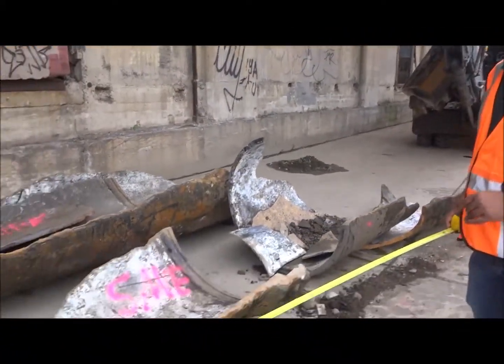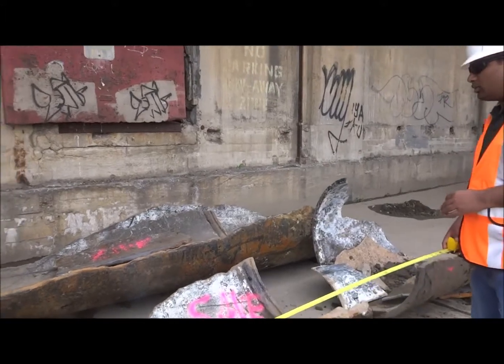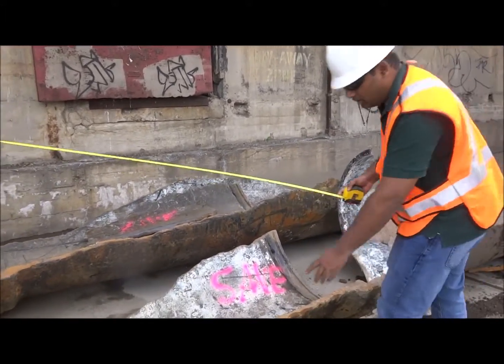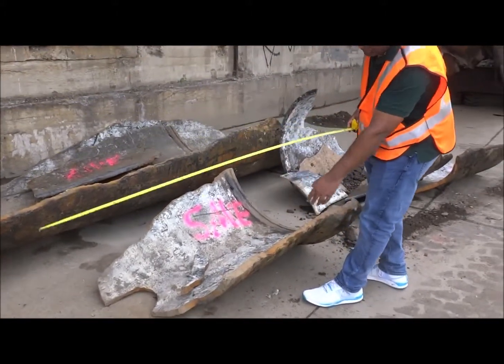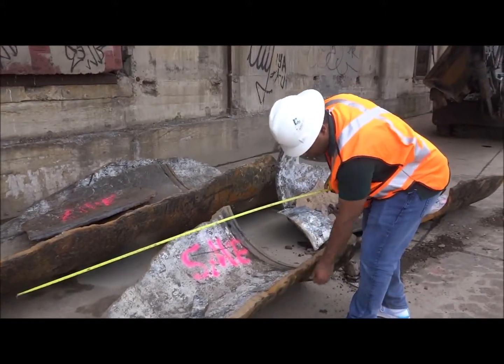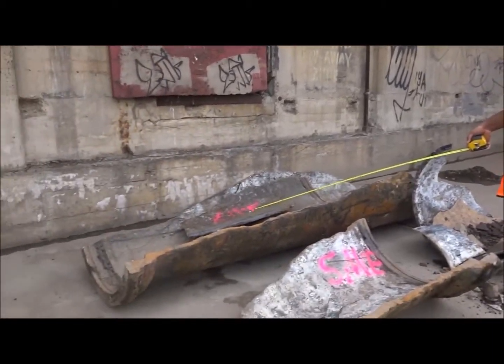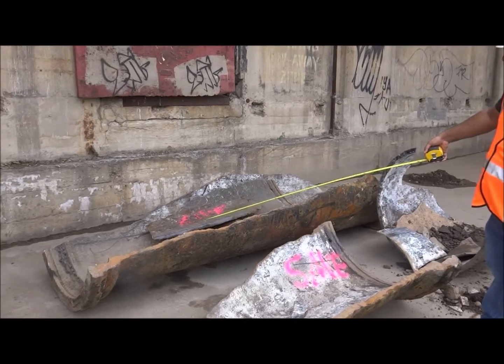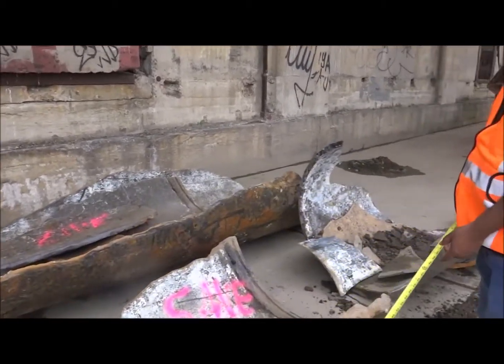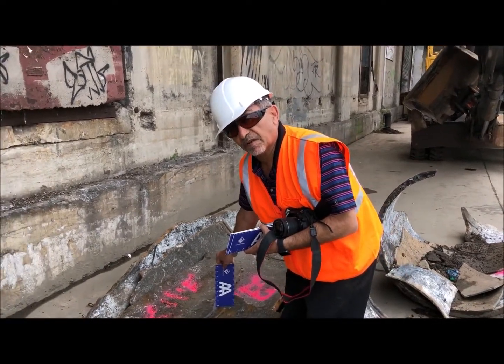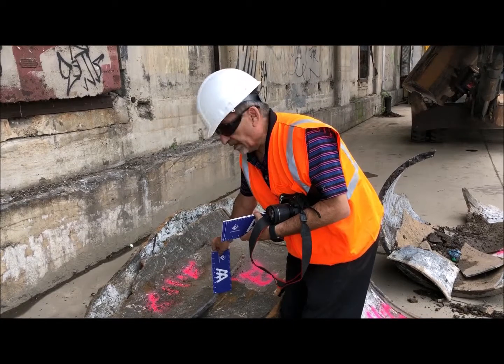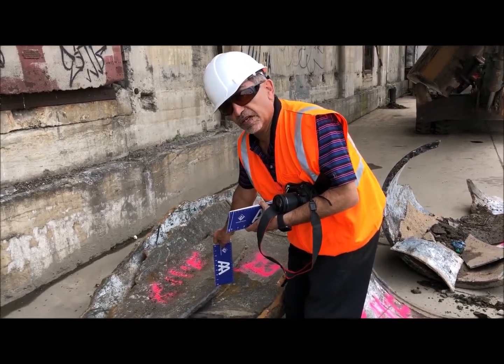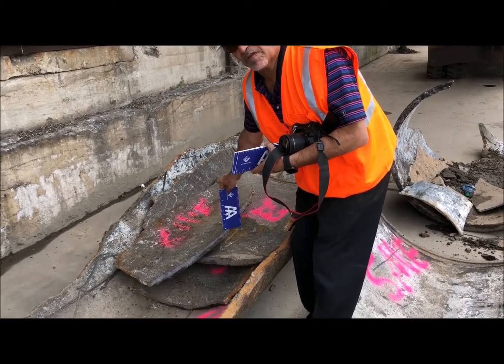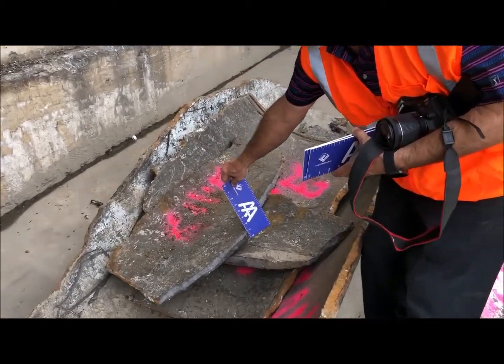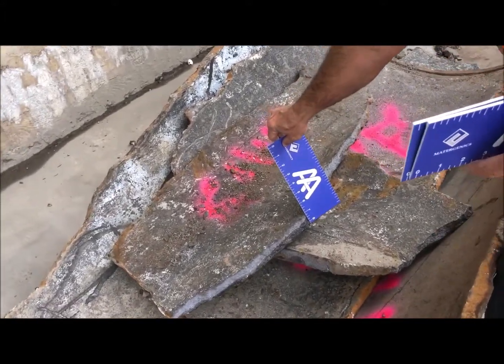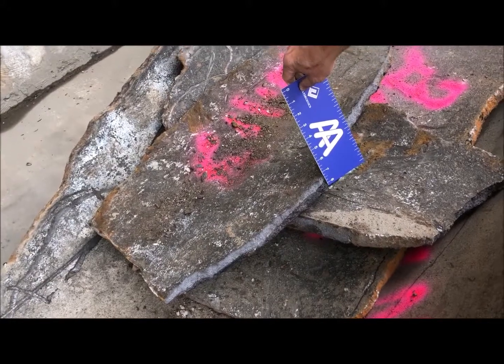This is the broken segment of the water pipe. From the appearance it looks like cast iron, and you can clearly see the thickness. This is the actual thickness of the sample, and here you can see the reduced thickness, and here where the tape is pointing you can see the indications of graphitization. Exhibits signs of graphitization. And more than 50% of the thickness in the fractured area is graphitized. That's why we have the failure. Please make a note here. That's great. Thank you.